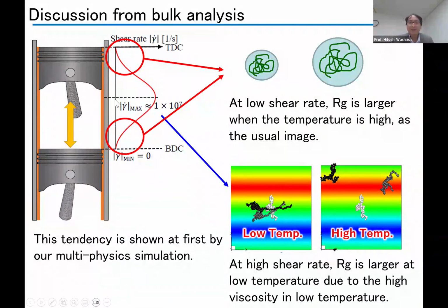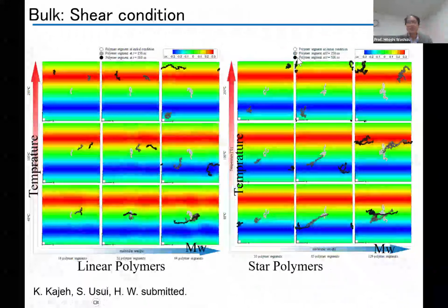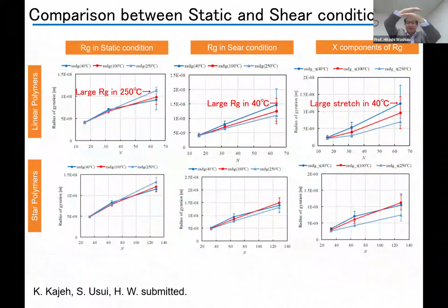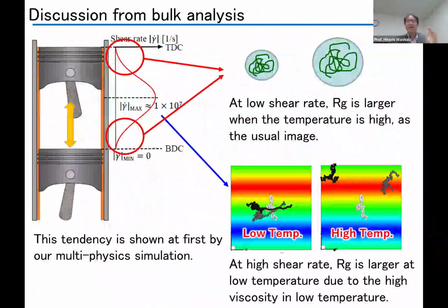Okay, in the high shear rate, the shear rate is high, so you don't need to enhance the viscosity. Here the polymers are stretched, so this does not affect the viscosity rising in the whole oil. This effect was not explained by experiment, but our simulation first explained this effect.